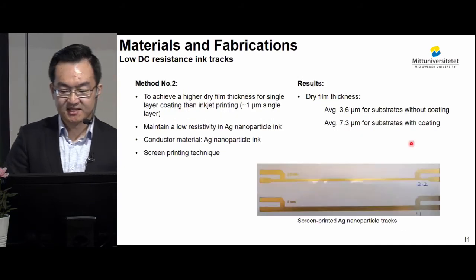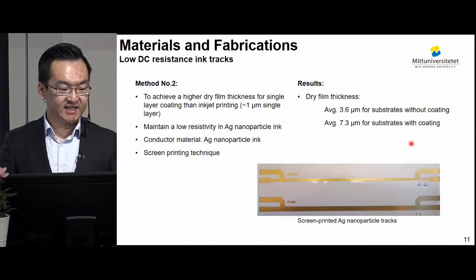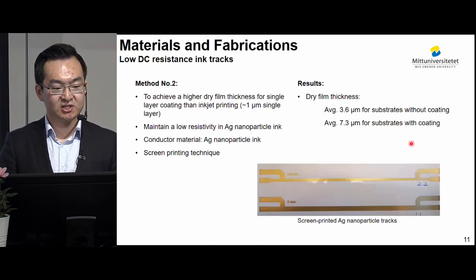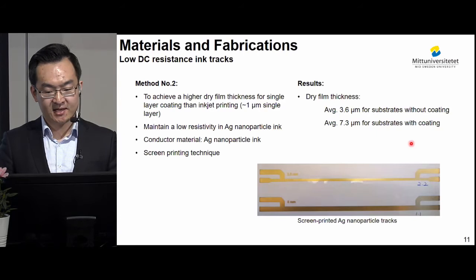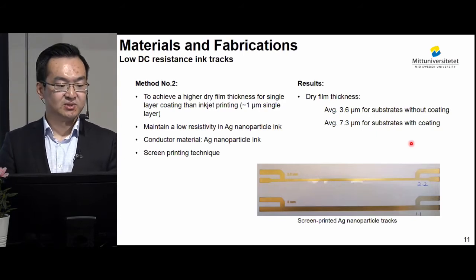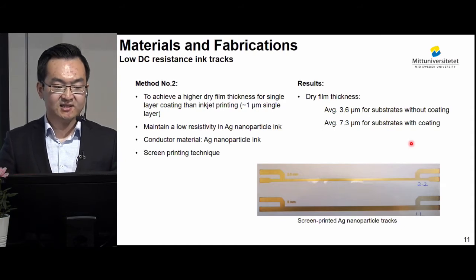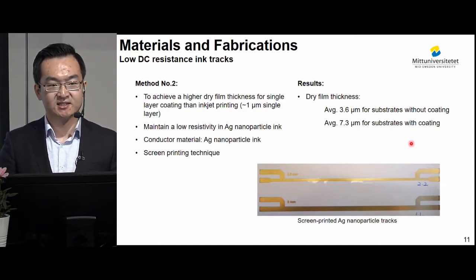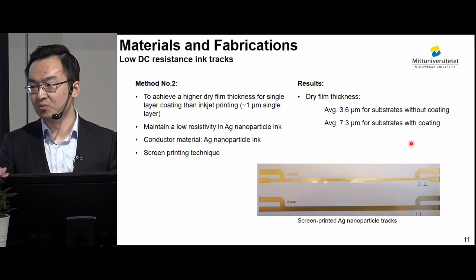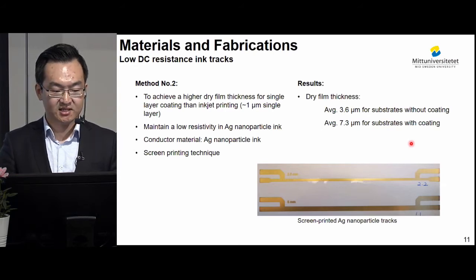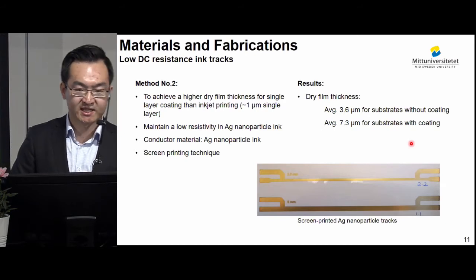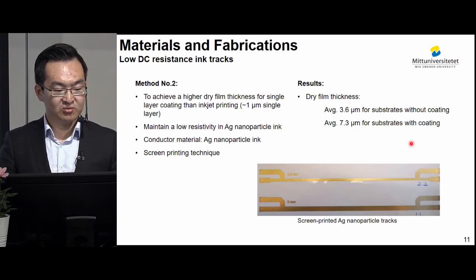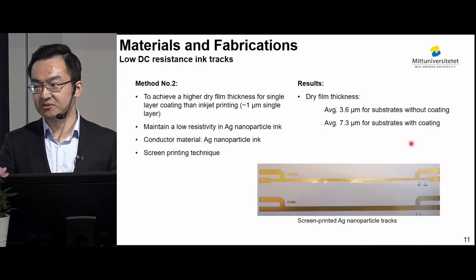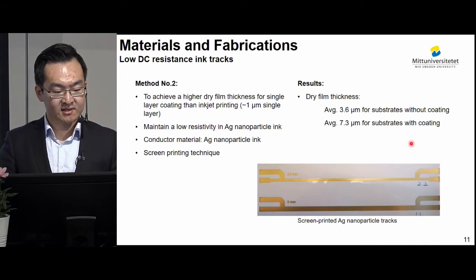The second method is to apply a screen printing technique on a silver nanoparticle ink. The objective of this method is to achieve a higher dry film thickness for a single layer coating than inkjet printed tracks, which is commonly only around 1 micrometer with a single layer. And in the meanwhile, we also would like to maintain the low resistivity advantage in silver nanoparticle inks.